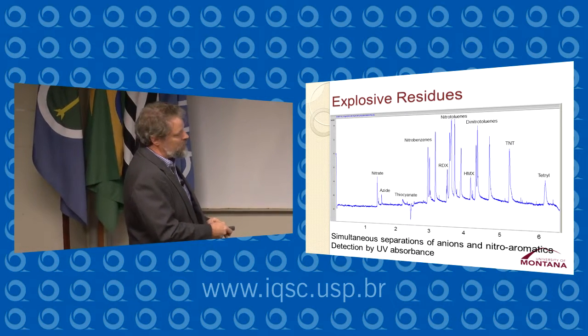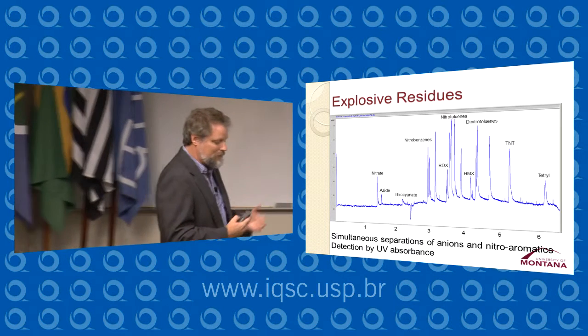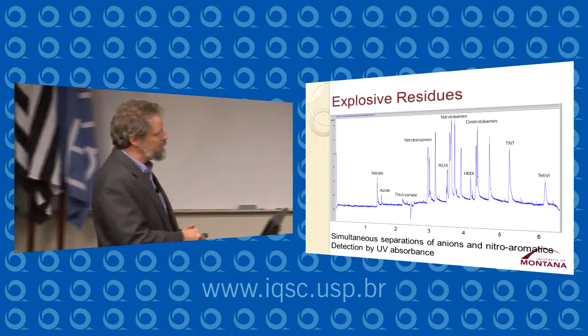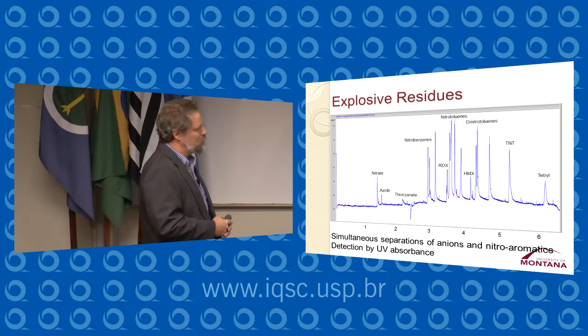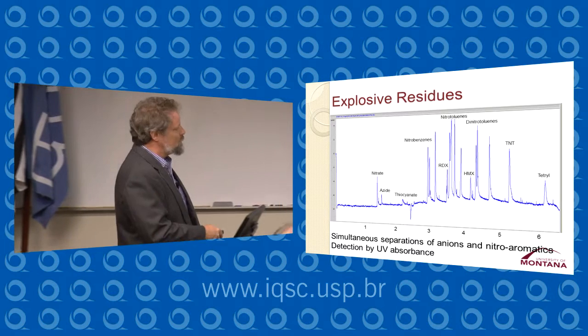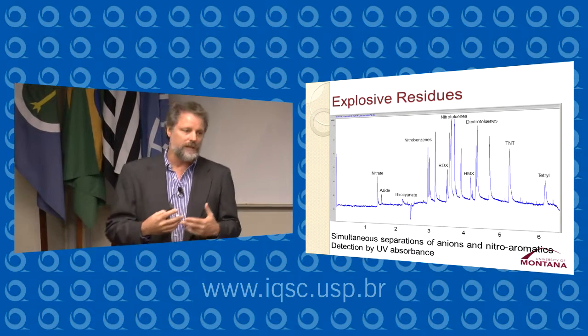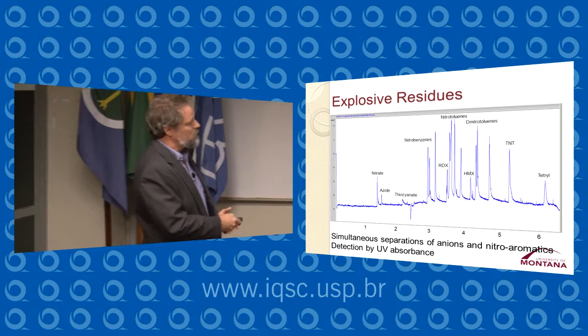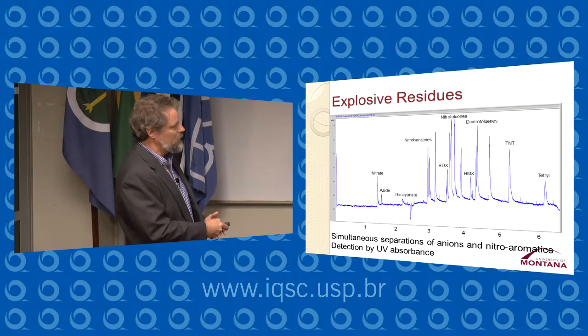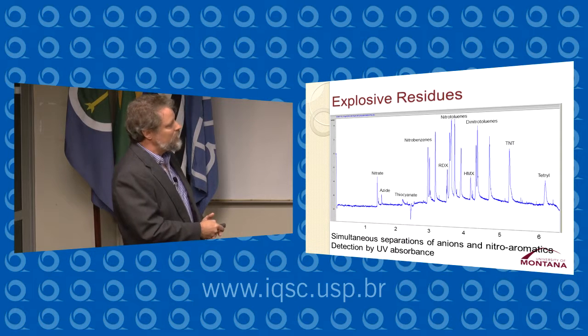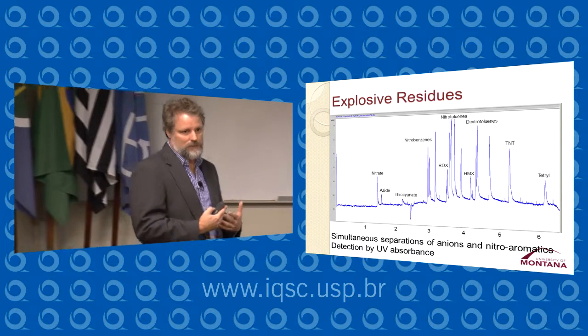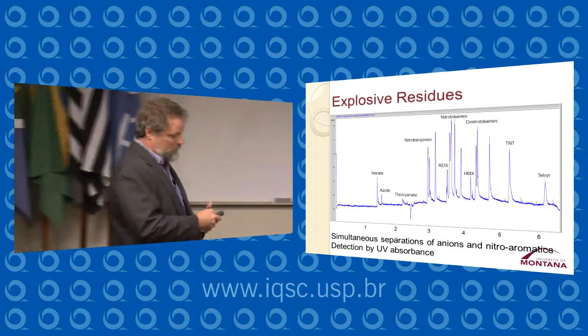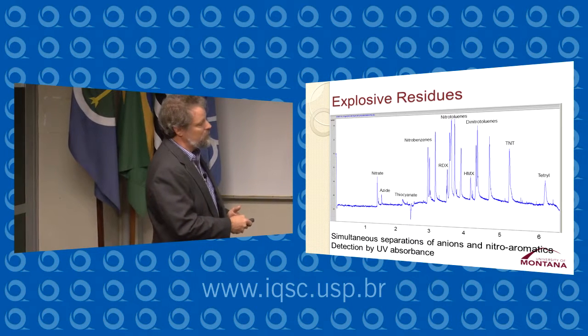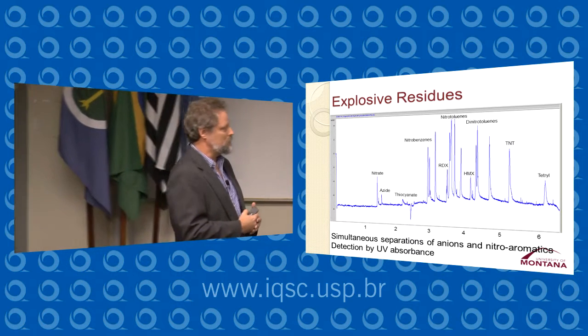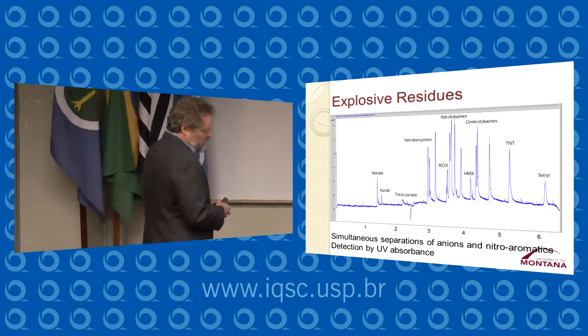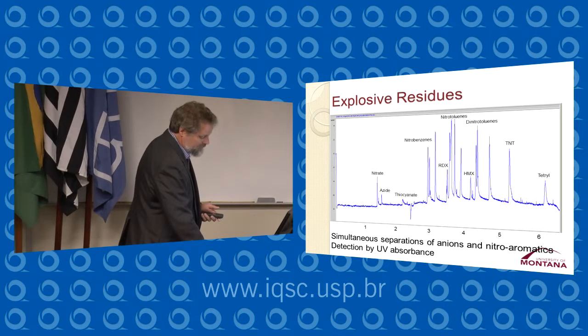It takes about 6 minutes right now. We need to make the people who are funding this work happy. We need to get that down to 2 or 3 minutes. I think we can do that. We're using UV detection right now. That's not ultimately what we'll do. We'll have two different detectors. One detector will be a conductivity detector so that we can determine the ionic compounds. And the other detector will be a fluorescence quenching device where the ability of these nitroaromatic compounds to quench fluorescence will be used to detect them. So we think we're making some pretty good progress now in this simultaneous separation.